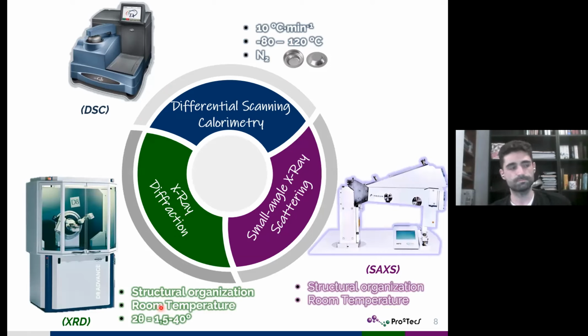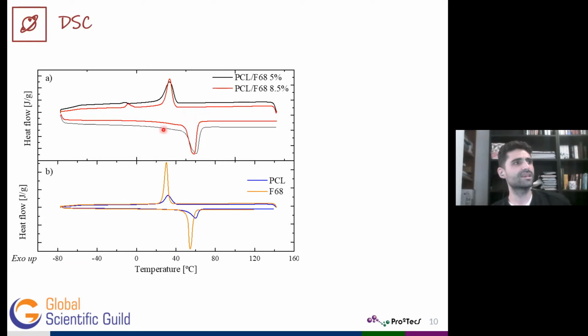Well, moving on to the results section, we can start with the DSC results. This graph shows the results of the pure compounds in the lower part, and the data corresponding to the polymer blends in the upper part, both containing the heating and cooling cycles. As we can see from the lower graph, although the melting temperatures of both pure compounds were quite close to each other, that thermal event was much more intense in the case of Pluronic in comparison with the PCL, even doubling the energy consumption during that thermal process.